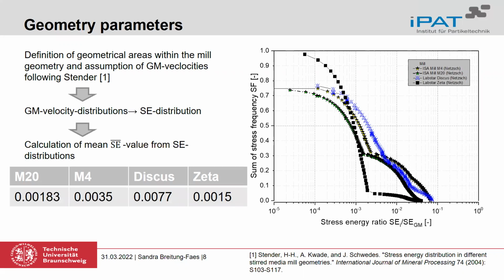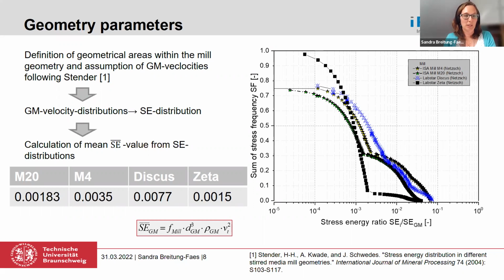Yeah. Good. So here are at least the values I calculated for the mean values. And here, as you can see, they are pretty different. And it's at least totally clear that these mills have a different, let's say, milling performance when you look at it. And so I included what I called a mill-specific factor into the stress energy to recognize at least the mean stress energy and not the maximum one, which would be the same for all the mills if you use the same process parameters.